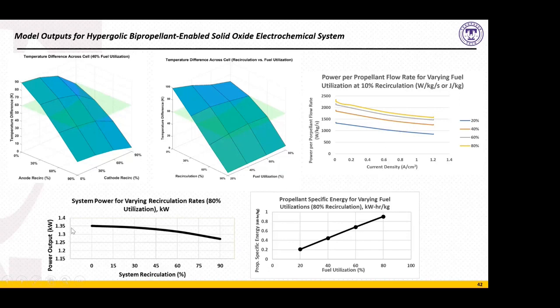We find here in the bottom that our power output does decrease, obviously, with system recirculation, but our efficiency will increase. We also have the propellant-specific energy for varying fuel utilizations here, and this is at 80% recirculation. We find that at 80% fuel utilization, the specific energy is about 0.9 kilowatt hours per kilogram. We can readily compare this to the theoretical value of the hydrazine NTO pairing, which is about 1.6 kilowatt hours per kilogram.